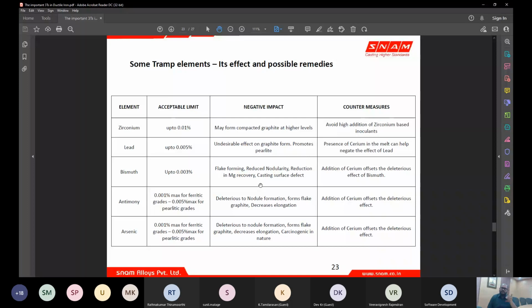So all these tramp elements can be controlled when it goes beyond your limit, when we go beyond your acceptable or controllable limit. You can have some special additives available into your liquid metal, like elements like cerium or lanthanum, like rare earth elements, which react with all these elements and let them not react with the carbon or distort the carbon. But this is not an excuse that you can keep adding cerium or lanthanum and you can still have more amount of arsenic, lead or zirconium.